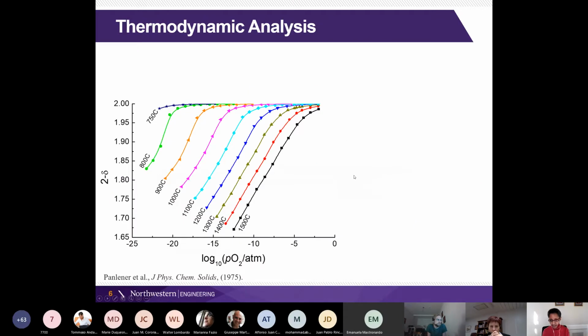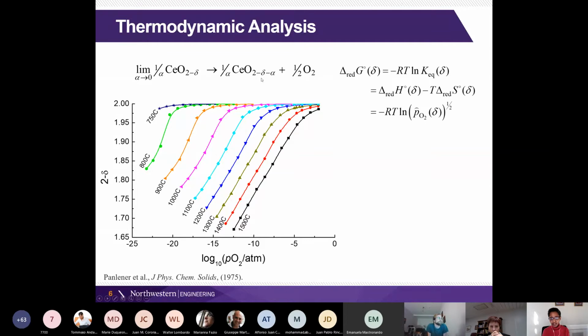And you may have heard this from Dr. Emanuele's talk, but let me add in here just how this looks. So let's say we have ceria undergoing reduction. So now we're going to look at this in infinitesimal change, and we have a delta G for that reaction. And we can write that out as being a delta G, which is at a given value of non-stoichiometry. So we're going to allow this alpha to go to 0. So we're imagining what an infinitesimal change in oxygen content would be, what that equilibrium would be for that reaction.